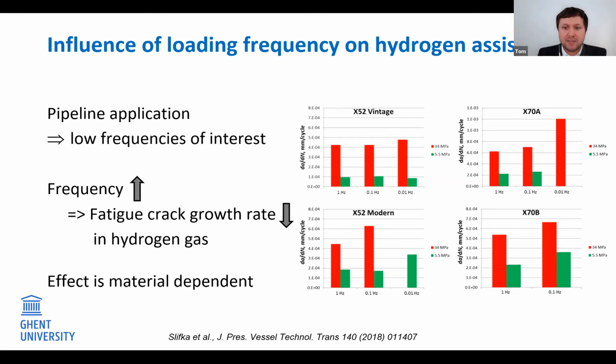And this could be explained by the difference in, again, this hydrogen diffusivity. And this is linked to the microstructure. So each steel has a different microstructure, and this comes with a different diffusion coefficient of your hydrogen atom. And this can be the reason why we see these variations upon different grades.